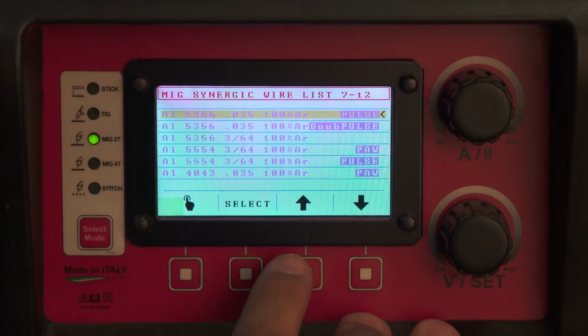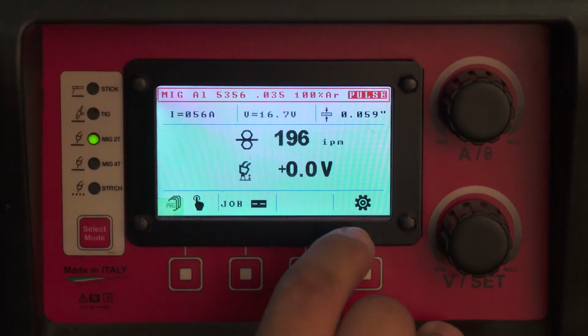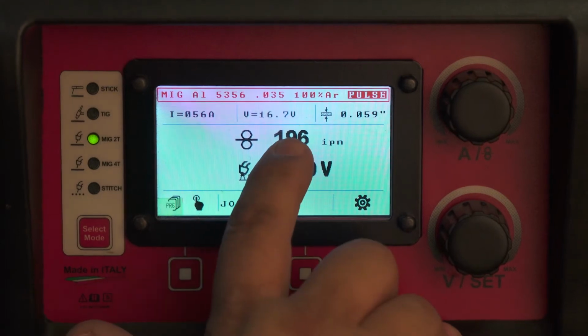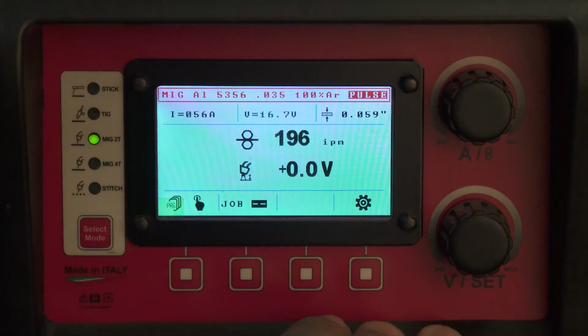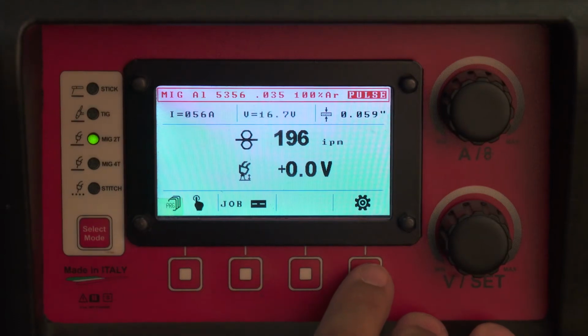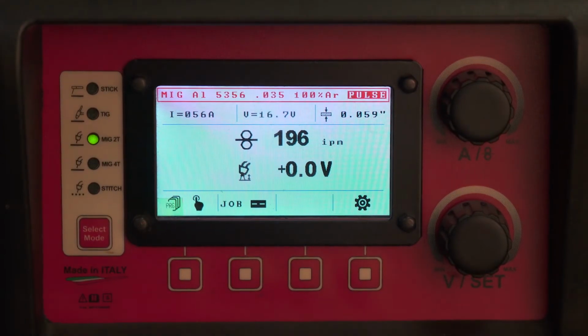Either one of those programs, you can select it, and then you see your material thickness here, your wire feed rate here, your arc voltage there, your predicted amperage over there. The reason why you would want to use pulse instead of just straight spray arc is it gives you the ability, especially in the PAW program, to weld very thin material on aluminum. It also gives you better control over the weld pool, and the double pulse program will give you improved looks of the weld, as well as significantly reduced heat input, warpage, and distortion on the base metal.